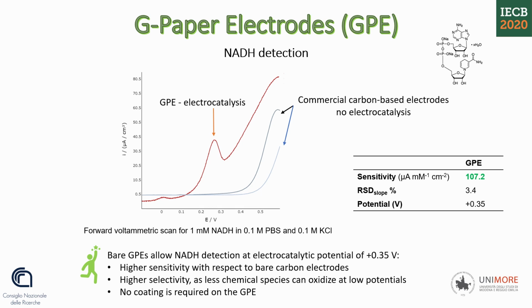We also performed flow injection analysis on graphene paper electrodes for NADH detection, and we observed great analytical performance, including a very high sensitivity and a very high repeatability of the response, without the need for a coating directly on the bare electrode. To conclude, we developed fully graphene-based electrochemical platforms which are suited for electrochemical applications, as our tests